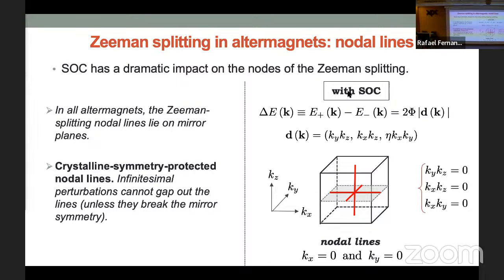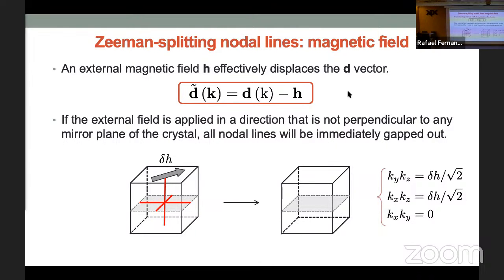What does it mean? It actually gives an extra stability for the altermagnetic phase. Let's say that I apply a magnetic field. Now if you apply a magnetic field, all these nodal lines should go away because I should get a Zeeman splitting, and the Zeeman splitting should essentially remove all the degeneracies. What is very nice is that in this formulation, in terms of the d vector, you can interpret a magnetic field as a shift of this d vector. And it's true that if I apply a field along an arbitrary direction, not a particularly high symmetry direction, I gap out all these nodes.